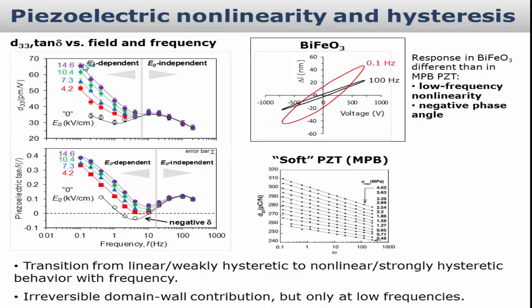So these domain walls will contribute to properties, they move, they contribute to macroscopic D33, but they're somehow restricted only to low frequencies, so they need time to move. And if you just think intuitively, you would see that there might be some correlation between domain wall motion and conductivity, because these are the frequencies where conductivity processes inside the material become important.